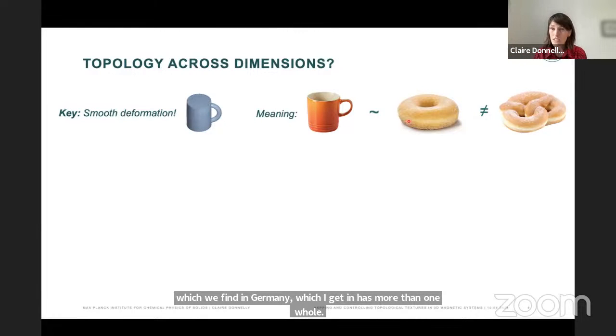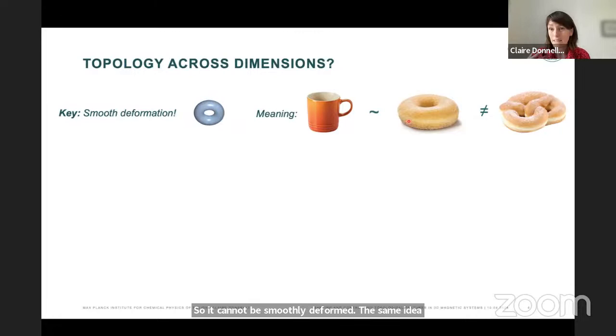The same idea of the smooth deformation happens in magnetization vector fields, where you treat the magnetization as a unit vector, and you can smoothly deform topological objects of the same topology into one another. Now, what this means is if you have topologically non-trivial objects, they cannot be smoothly deformed into a uniform magnetic state, and therefore they have the potential to have associated topological stability, so to speak, which means basically there's an energy barrier associated with their transformation into, or their disappearance into, a uniform state.